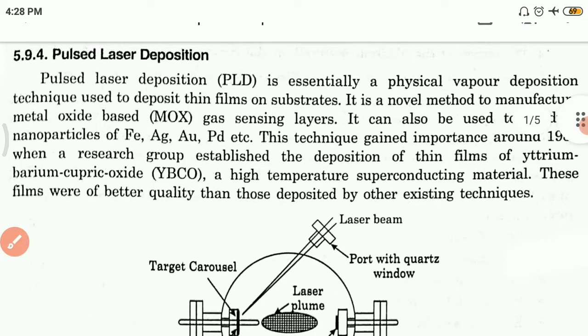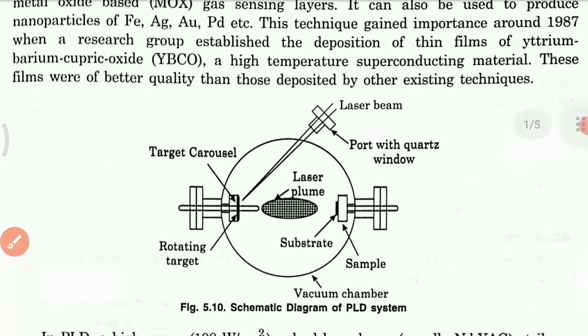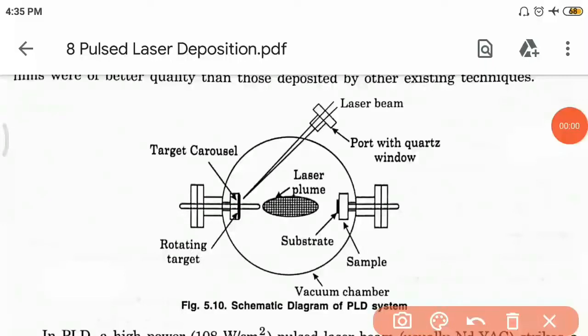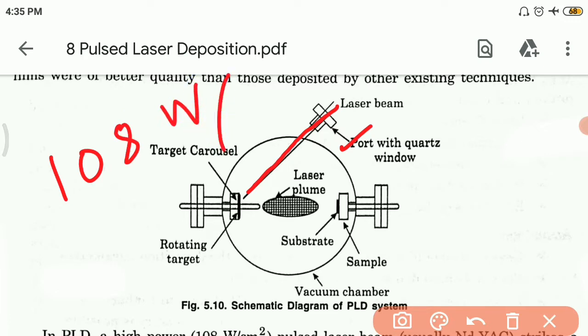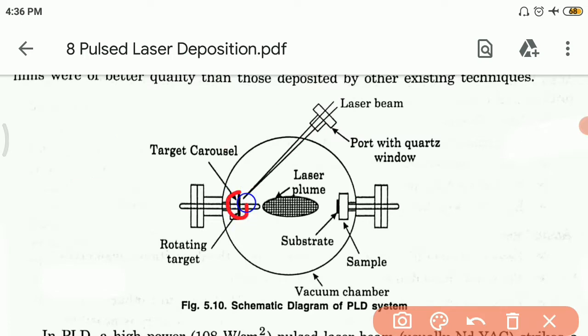Now you can see this is the schematic diagram of the PLD system. Now let us see how it works. Here a pulsed laser beam, with a high power of around 10^8 watt per centimeter square, enters through the port with a quartz window, and it is usually Nd:YAG, that is neodymium yttrium aluminium garnet. This laser beam strikes the rotating target of the material which is to be deposited as a thin film. The target and the substrate are placed inside an ultra high vacuum chamber.